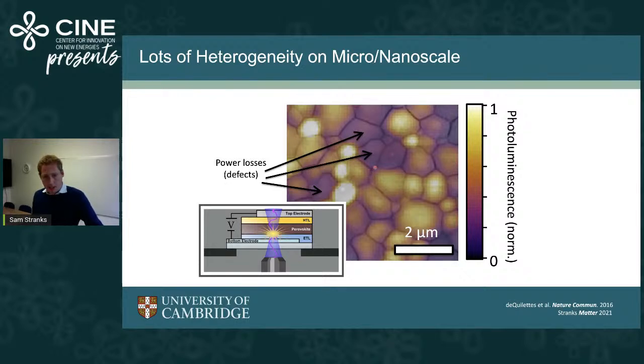What's really quite striking is that some of these grains are really dark in luminescence. If you remember, I told you how these dark regions correspond to luminescence losses and defects. So that's what these correspond to here. Whereas there are other regions that are very bright and luminescent, and this is what we want in a solar cell. We ideally want this image to be uniformly bright. So this shows us that there are losses in these materials, and even in the most high-performing devices, we do still see these non-radiative losses.